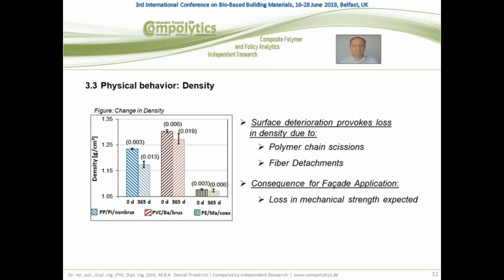Then we also measured density, and we can see a significant decline in density after 1 year, which is pretty much due to polymer chain scission and fiber detachments, which makes the mass going down after 1 year.